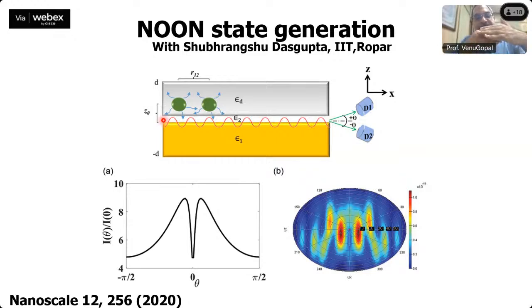and bring it very close to the metal surface and excite one of these quantum dots. This quantum dot's emission is able to excite the plasmon mode at the metal-air interface. Air is in between, the dielectric epsilon d and epsilon 1. The epsilon 2 can be air or any other dielectric. If you consider air, simply at the metal-air interface the plasmon mode is excited. This propagating plasmon mode excites the second quantum dot and makes these two quantum dots coupled together, because of which we showed that the emission coming out of this structure is a NOON state.